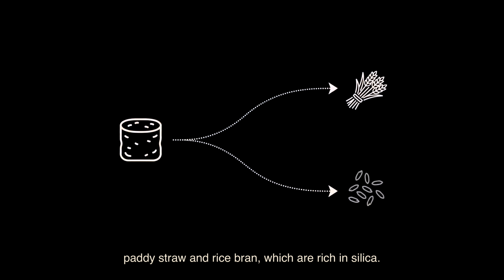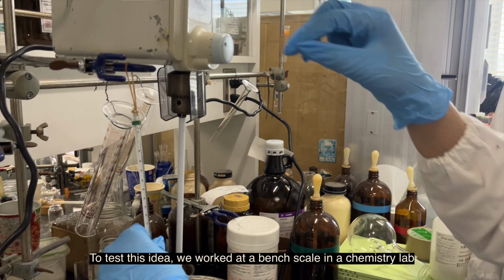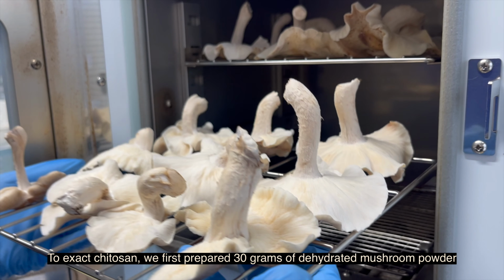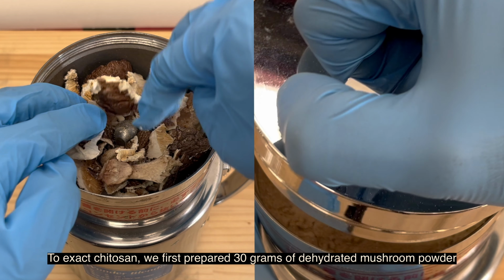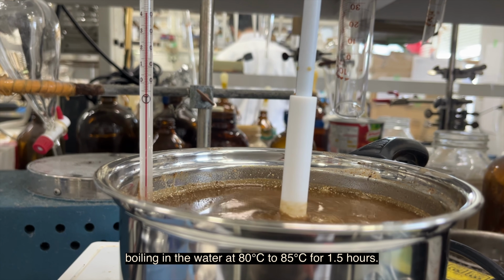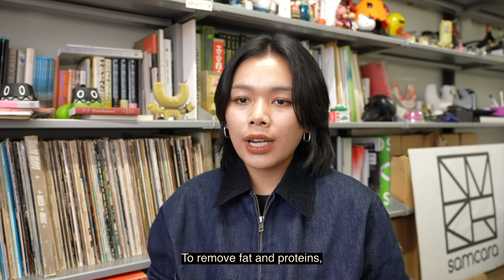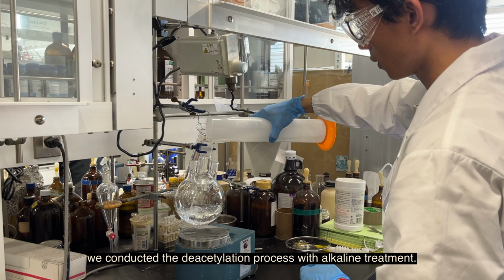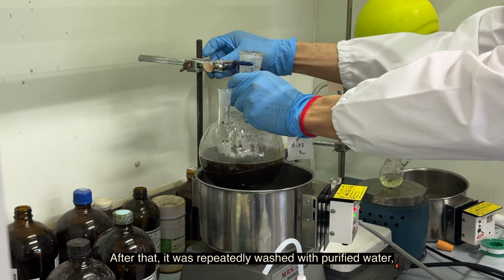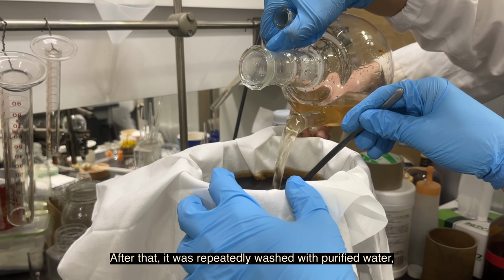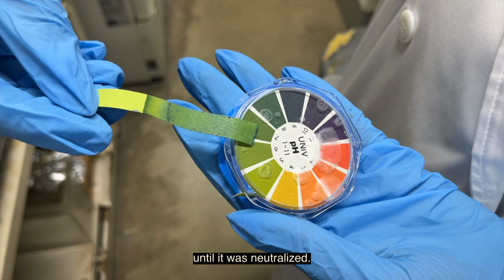To test this idea, we worked at a bench scale in a chemistry lab. To extract chitosan, we first prepared 30 grams of dehydrated mushroom powder for the warm water extraction, boiling in water at 80 to 85 degrees Celsius for 1.5 hours. To remove fat and proteins, we conducted the deacetylation process with alkaline treatment. After that, it was repeatedly washed with purified water until it was neutralized.